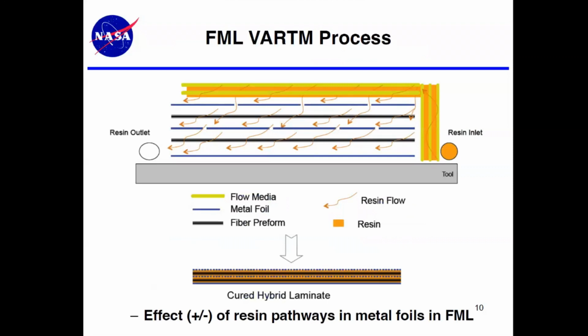If the infusion was only along the direction of the part itself, it would take an extremely long time. So the flow media allows the resin to flow through the thickness and make the part in a much quicker process. So this is a side view of the process itself. You can see the flow media is depicted there in orange and yellow. The metal foils are in blue, and then the preform or fabric material is shown in black.